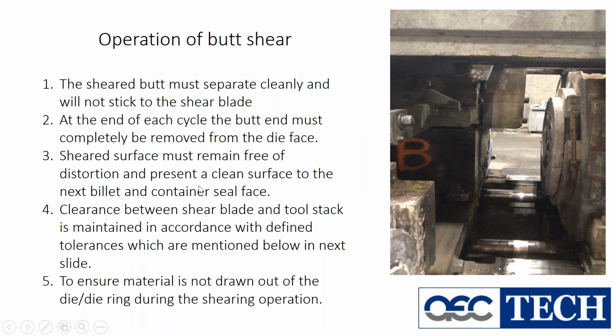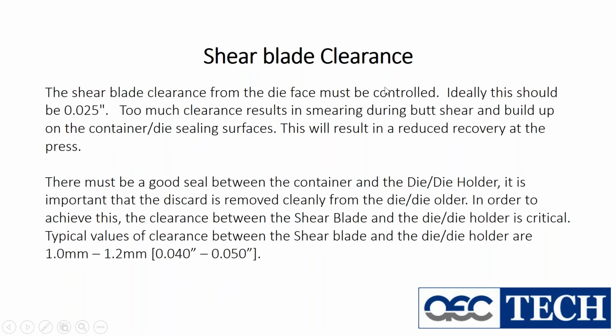So this is where we were. Shear blade clearance. From the die side, the die face must be controlled. Ideally, 25 thou. Too much clearance is going to leave too much aluminum. Even if you shear it straight, there's going to be too thick of a wafer of aluminum left on the back of the die, which will then smear and pull back up or down, and then it'll start to build up on the container seal face.